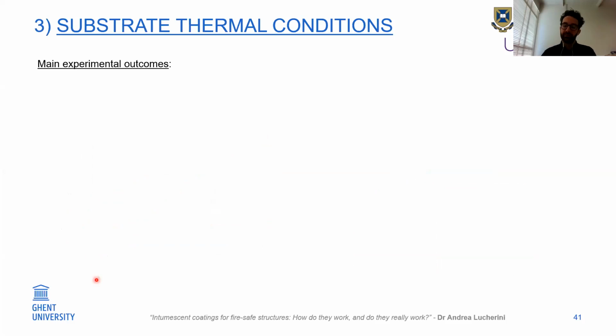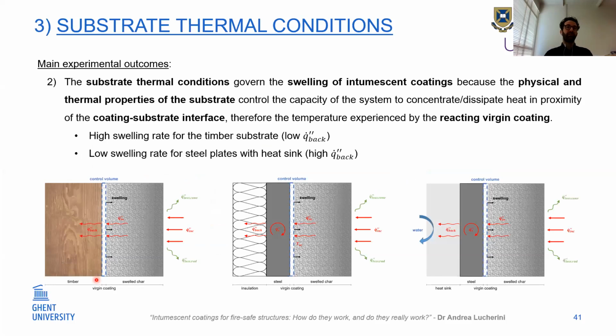And this is because of the substrate thermal conditions that govern the swelling of intumescent coatings, because of the physical and thermal properties of the substrate. So in particular, what is the capacity of the system to concentrate and dissipate heat in proximity of the coating's substrate interface, where I showed you earlier the reaction happens, and is the temperature that the reacting virgin coating